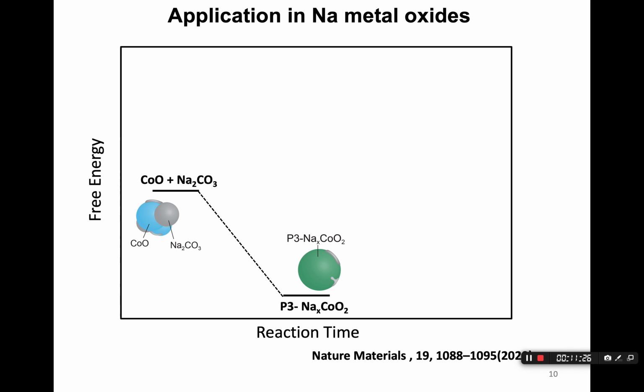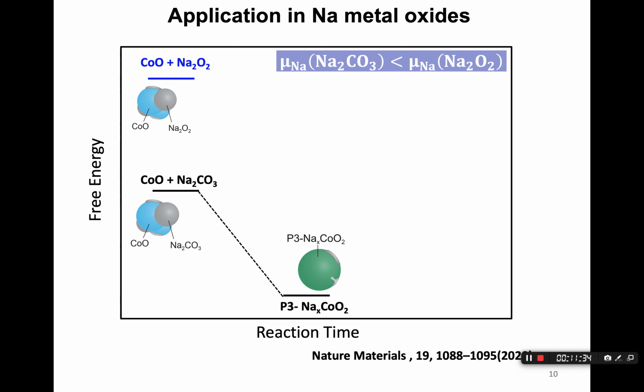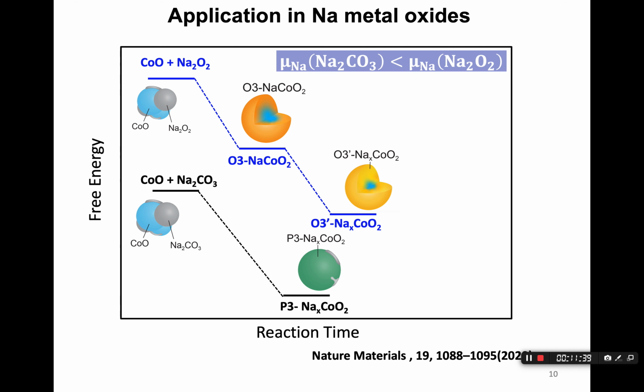However, if you play with the precursor a little bit, for instance, if you use sodium peroxide, it's actually going to form something very different. They're going to form an O3 phase accompanied by an O3 prime phase. The reason behind that is you are basically changing the chemical potential of sodium, because the chemical potential of sodium is larger in sodium peroxide compared with sodium carbonate. So in that case, you are basically raising up the energy landscape so it can hit some metastable energy state, which is O3 or O3 prime sodium cobalt oxide.